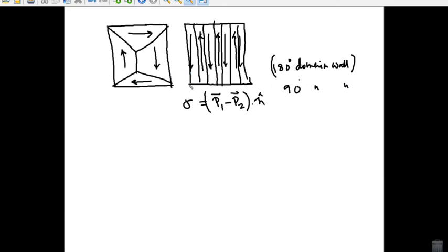The presence of domain walls involves other energy costs. Firstly, the domain wall is microscopically different from the bulk, and the energy gain in forming the polarized ground state has been lost. Secondly, the polarization is coupled to elastic strain, as we saw above, and we must also make sure that the strain fields are compatible. There is no difficulty with a 180-degree domain wall, but a 90-degree domain wall produces problems, and the ideal configuration is by no means ideal in terms of the strain fields.